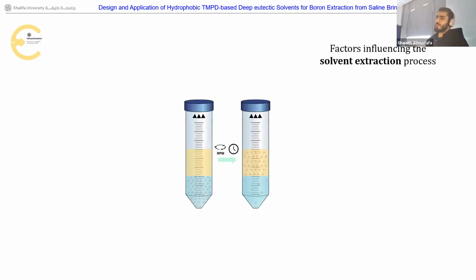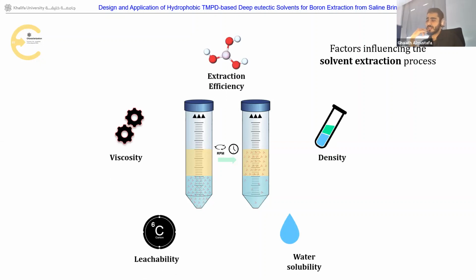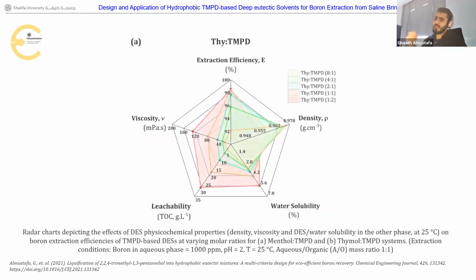Now, furthermore, for the characterization step, we wanted to know what kind of factors are influencing the solvent extraction process. And these are factors such as density, viscosity, water solubility, and the leachability through TOC. And these are all related to the extraction efficiency per se. So we plotted and visualized those properties for each of the components in the same graph. And you can see that there is a significant effect of those properties on the extraction efficiency as well.